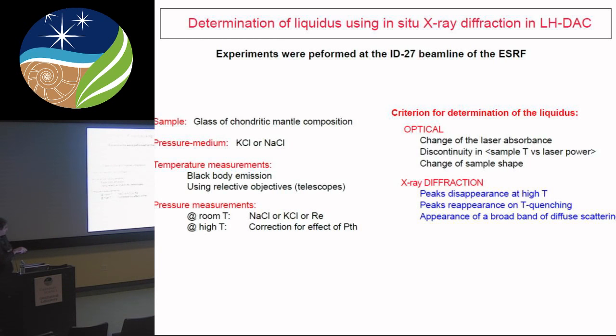We found that the best criterion we had was this one: peak reappearance on quenching temperature. Of course, we follow progressively the disappearance of the peaks. But when everything is almost molten, because you still have a few grains that crystallize close to the pressure medium, when you decrease temperature and many peaks reappear, this really means that you've been melting almost everything or everything.